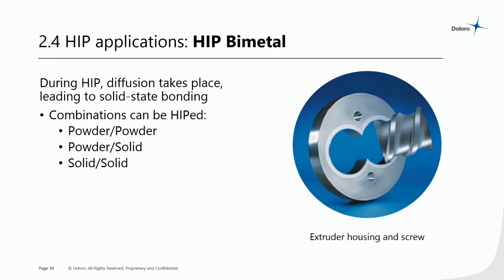Why would we want to do this? Well, if you have, for example, an internal diameter that's really deep and really narrow, you can't do that by welding. You can't apply your hard facing by welding, for example. You also can't make it necessarily by casting it because it's a bimetallic structure. So the answer is to actually use HIP to apply the second alloy as a powder into the inside of the body, steel body, for example.